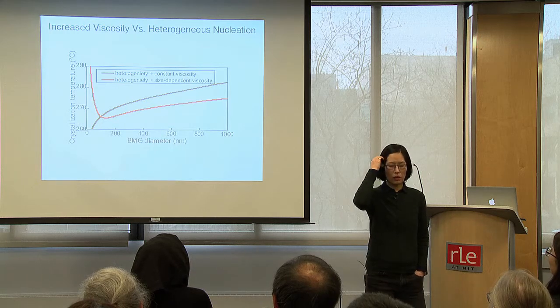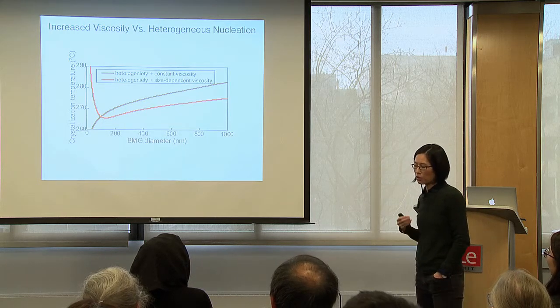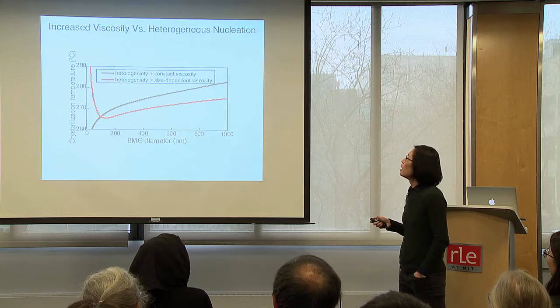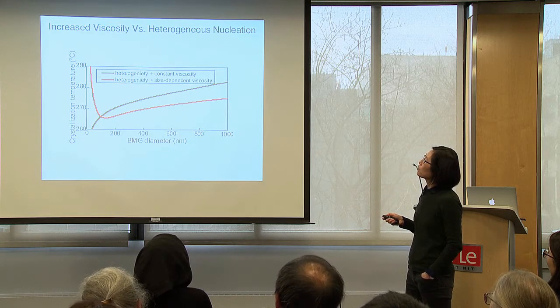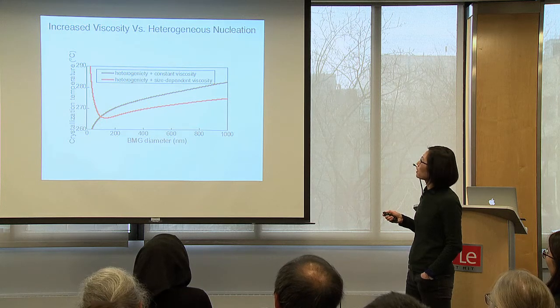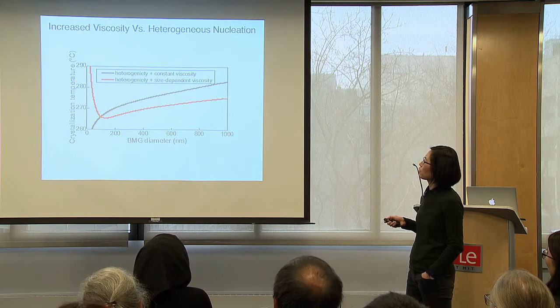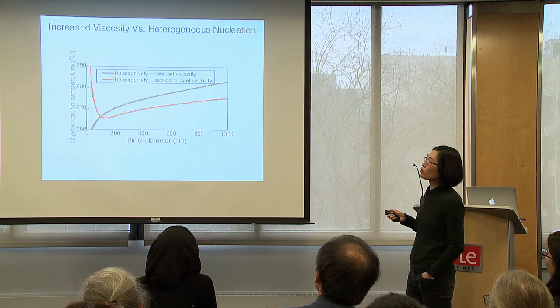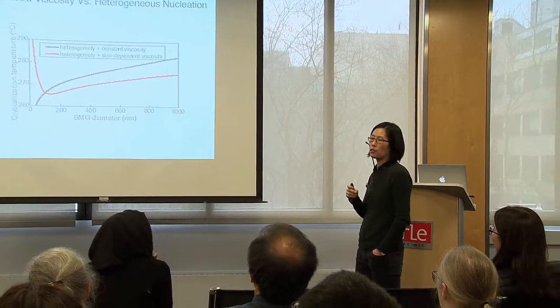Later, near the end of the talk, I want to go back and try to give you reasons why that may be. So if we include the heterogeneous nucleation, which can explain the first decrease in crystallization temperature for larger rods, and also the fact that the growth rate slowed down. Another way to say it is that the viscosity, which is 1 over diffusivity, is size dependent, then we can recapture what we observe pretty well. Okay. So that was our first work. Okay, so we summarize and wrap that up.